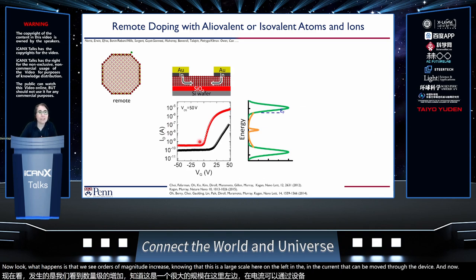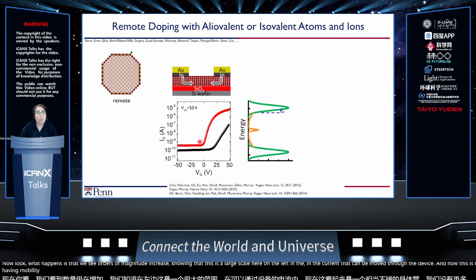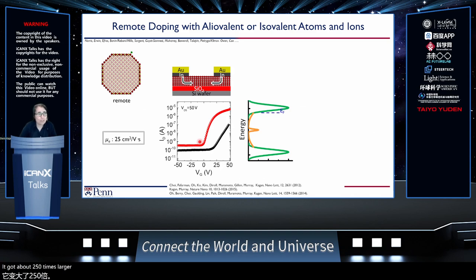device. And now this is looking like a pretty respectable transistor, where instead of having mobilities of 0.1 centimeters squared per volt second, it got about 250 times larger, right? So we could prepare devices with mobilities of about 25 centimeters squared per volt second. The way that we think about this is that once you dope the material, you add electrons, the Fermi level moves up, and now you have many more electrons that sit in these higher density, higher mobility states so that we can more readily move charge through the material.